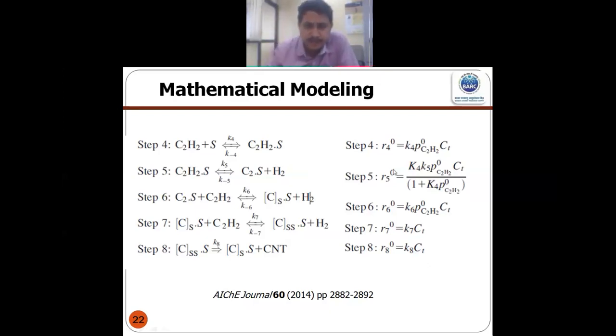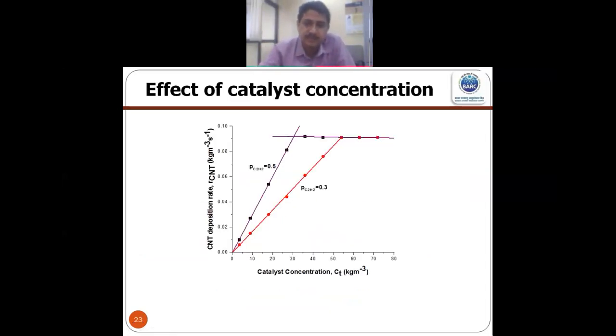Because if I see the CT, which means catalyst concentration, in all these equations you can see catalyst concentration varies linearly. So now if I vary the catalyst concentration against CNT deposition rate, actually experimentally we carried out, we found that yes, it is varying linearly, and after it reaches some saturation value, but at different partial pressure they linearly vary with the catalyst concentration.